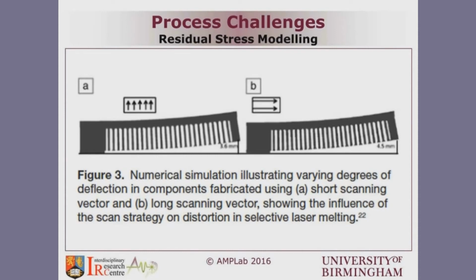The amount of relief from releasing the stresses can be used qualitatively to indicate the amount of distortion. But the key point is that the process itself can be rather complex, and one change in a parameter—in this case the scanning strategy—will control the thermal fields and, as a result, affect the amount of distortion from the process.